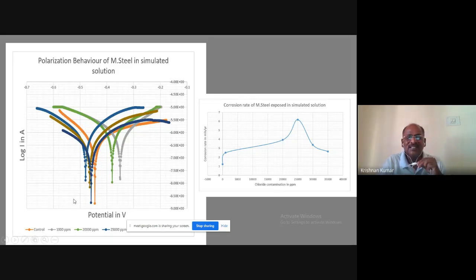So that means corrosion is happening spontaneously, and the corrosion is very aggressive when the chloride ion concentration is more. Based on this, we have calculated the corrosion rate, how much corrosion is occurring in that particular solution, and we have mapped it. Here we can see that at 25,000 ppm the corrosion is very high. Beyond that level, the corrosion is not much. Then the question arises: even though a higher ppm level is available, the corrosion is less.